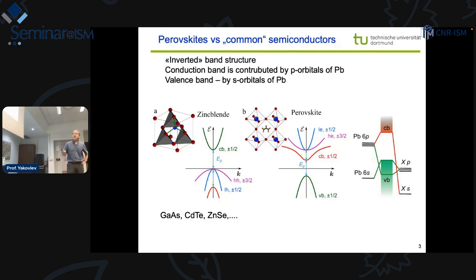But there is more, because now the valence band orbitals are formed by the s orbitals of the lead ions, not by the p orbitals like in common semiconductors. And the conduction band is formed by the p orbitals. For spin physics, this becomes very important, because we also have interactions of the band carriers with the nuclear spins. To have the maximum of these interactions, we need s orbitals, where the carrier has a maximum at the nucleus. It's known for gallium arsenide, for example, that the hole hyperfine interaction with the nuclei is nearly 0. And it will be the other way around, the maximum, in the perovskite materials.